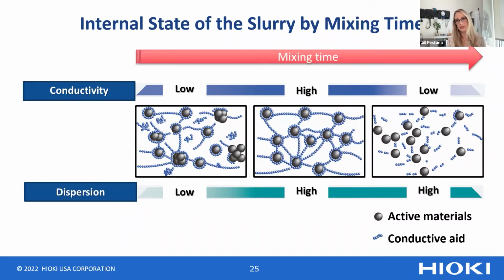But as you increase your mixing time, like if you're mixing cake batter, muffin batter, whatever you want, you're eventually going to get a higher level of dispersion. And that's when you get that conductivity network happening in the slurry after it's been mixed a bit. But if you mix it too much, you can disperse the materials too much, and those conductive networks may go away. And so you may think, okay, I just know how to optimize a slurry. I just mix it for a really long time. It turns out that may actually decrease the conductivity of that electrode over time.